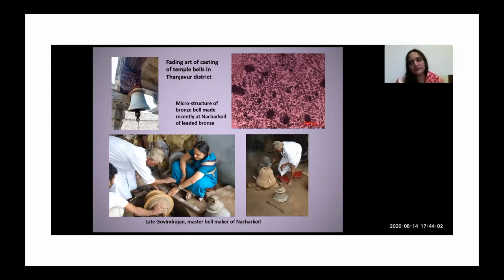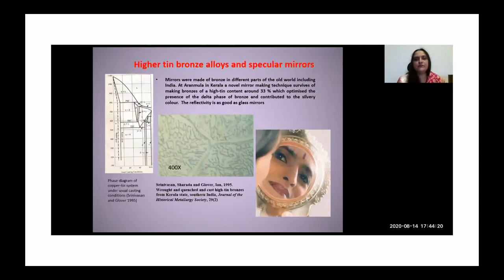So the bells had a different composition. But this is a modern one, so we have to really try and understand what was going on with the traditional bells and such like. Probably this actually has a bit more tin, probably closer to 20, but it's not quenched. And that's why you see all that silvery white phase.